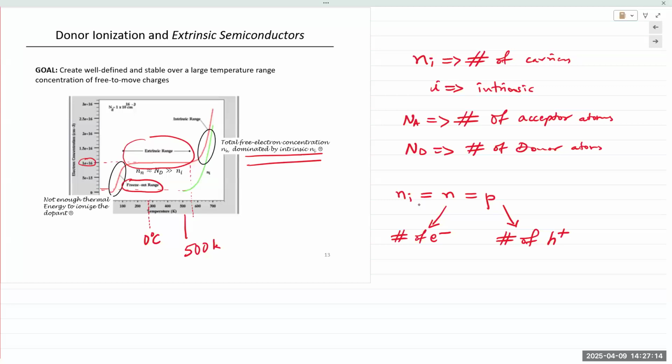intrinsically, thermal generation. We cannot have a hole created without an electron being generated, right? So a free electron generated by breaking its bond also generates a positive hole at the exact same time. So they always go together, they always go hand in hand. Hence, they are known as electron hole pairs. Electron hole pairs. And that process is known as generation. This is a very important process. So every time an electron acquires thermal energy, breaks its bond, it generates an electron hole pair.